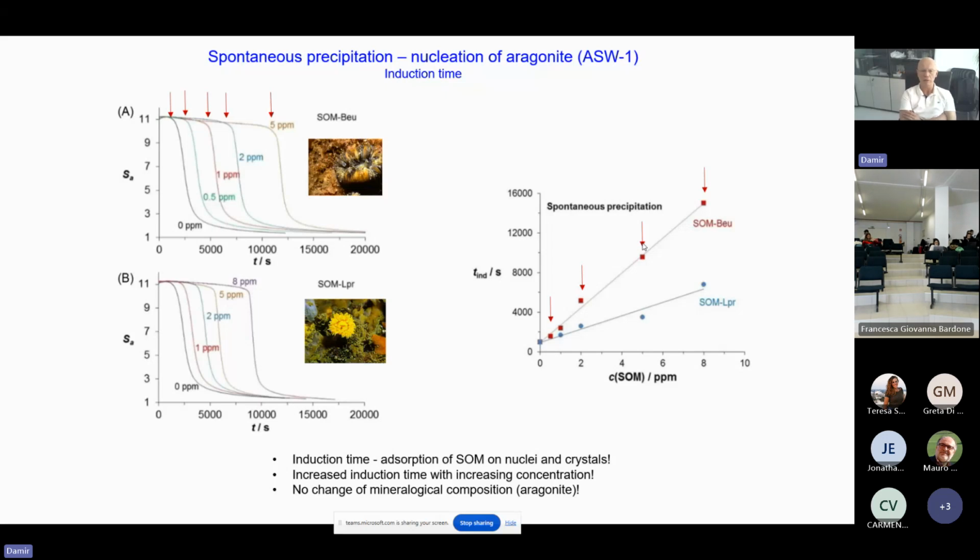And indeed, we find out that, so this is a model system. We can obtain precipitation after a certain period of time, and precipitation ended at supersaturation that is about 1. It converged to 1, so it means it is approaching the equilibrium. This is precipitation of aragonite.